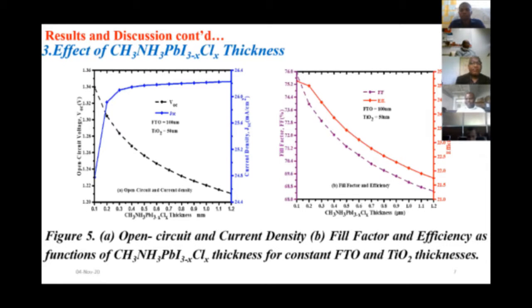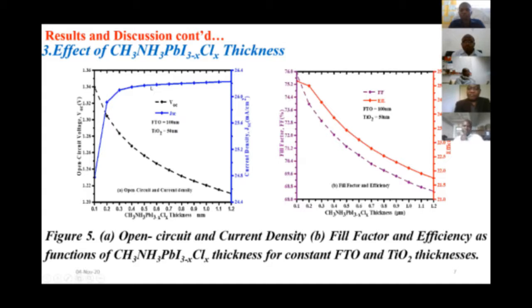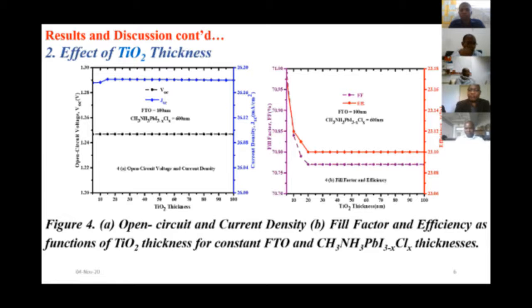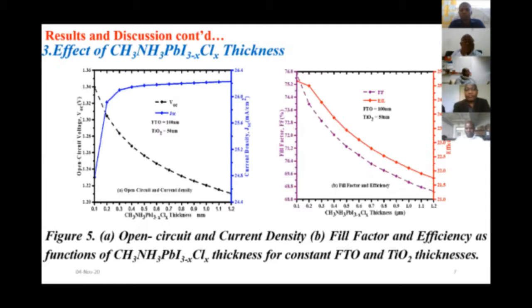Then for the absorber layer, we realized that an increase beyond about 400 nanometers impacted negatively and reduced the performance of the cell. So we took 300 nanometers for the absorber layer as our optimum. For TiO2 we took 50, and for FTO we took 100 as our optimum layer thicknesses.